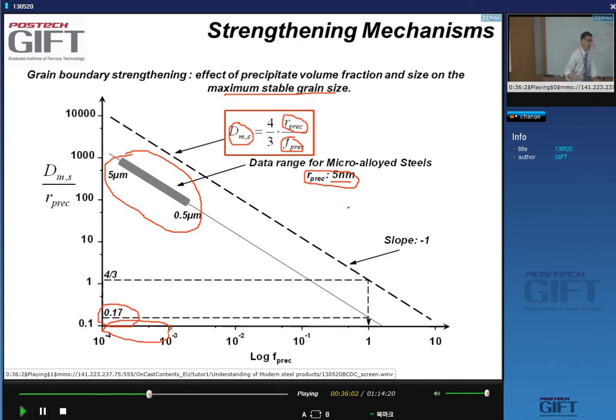Very often, the strengthening mechanisms of materials are presented in a discussion of particle strengthening. And it's always forgotten that at the same time you do particle strengthening, you also control the grain size. In fact, in conventional HSLA steels, these niobium HSLA steels, the strengthening doesn't actually come from the precipitation, but most of it comes from grain size reduction through this grain boundary pinning mechanism.